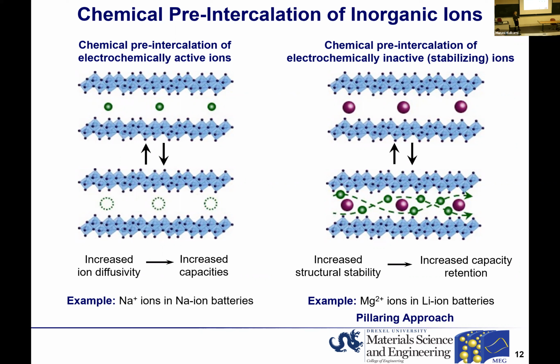First, we can chemically pre-intercalate electrochemically active ions, the same ions that are being cycled in the battery. An example is sodium ions in the case of sodium-ion batteries. In this case, during synthesis, the ions already create sites that are favorable for these types of ions. So we hypothesize that we can improve diffusion through this material synthesis.